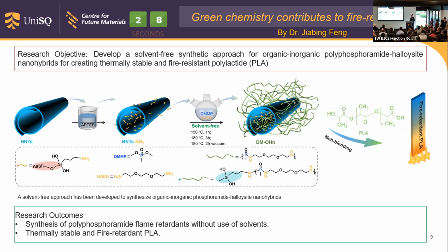We don't use any solvents, but successfully synthesized this polyphosphoramide-based flame retardant. And then it shows excellent flame retardancy in PLA. Finally, we achieved the green synthesis of polyphosphoramide flame retardants without use of any solvents. And then we obtain thermally stable and fire-resistant PLA.